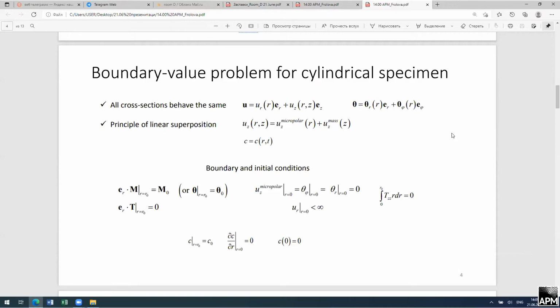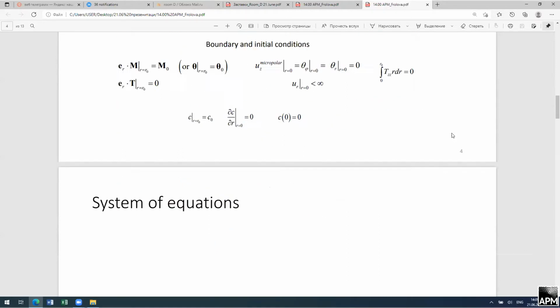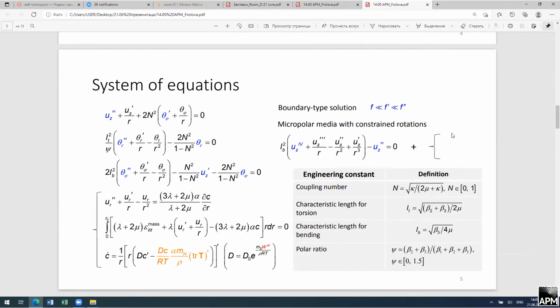And we use the following boundary conditions. We assume that the lateral surface of the cylinder is traction-free and also set distributed couple stress, or micro-rotations, that model real rotations of regions between microcracks. We also assume that the axis is fixed and find radial displacement as usual, and use the Saint-Venant principle and an integral boundary condition at the end faces of the cylinder. And as for boundary and initial conditions for concentration, they are the same as in the experiment. So we solve the following system of equations.